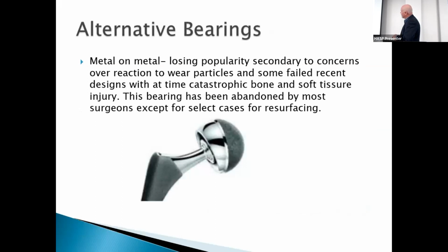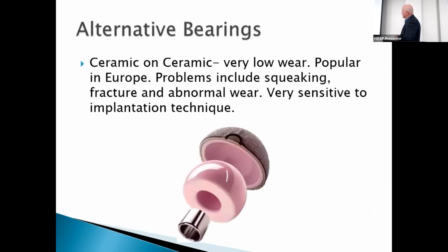Again, we talked about the metal on metal and alternative bearings. And here's a picture of a ceramic on ceramic. Great concept, but it has had lots of problems with chipping at the edges of the socket. If the hip goes through range of motion and the neck of the femur hits against it, it can chip, and then that can cause small particles of plastic or of ceramic to get in between that surface, and then that can cause catastrophic wear and failure over time.